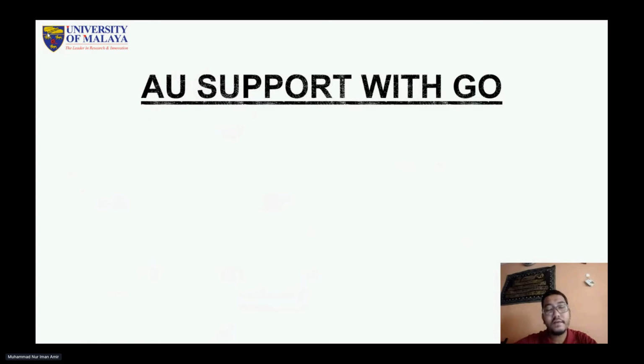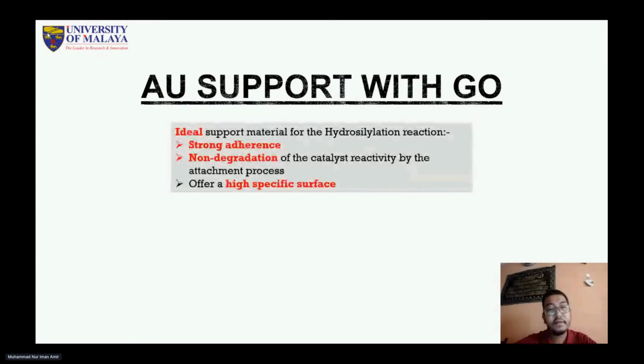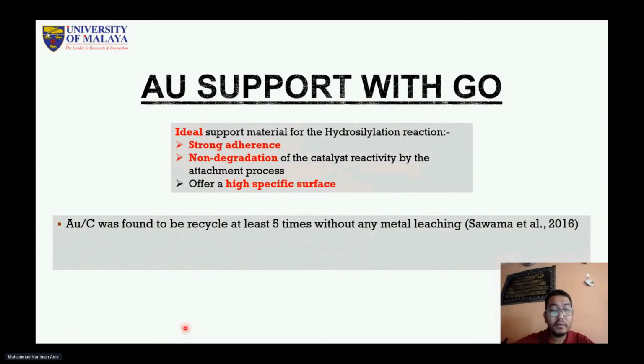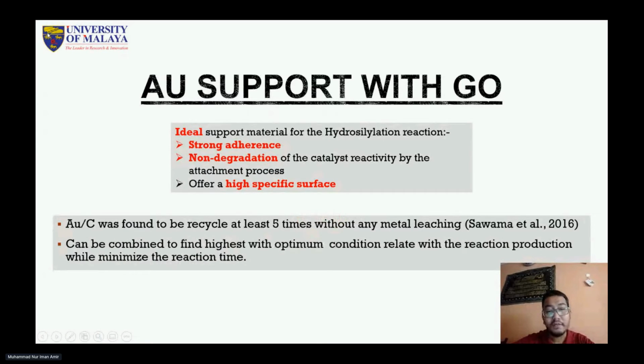And gold supported on graphene oxide, you can say, is an ideal support material for that reaction because of the strong adherence, the non-degradation of catalyst reactivity by the attachment process, and it can offer a high specific surface area. Based on previous studies, the gold carbon catalyst can be recycled at least 5 times without any metal leaching. Our target is to achieve the highest production with optimum conditions while minimizing the reaction time.